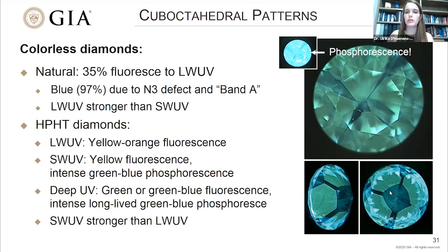Again, these stones are going to have very, very strong, intense, long-lived phosphorescence, which is going to help us flag these stones as potentially synthetic. And by long-lived, I mean very long-lived. Some of them can phosphoresce for several minutes, whereas natural diamonds are going to fluoresce for a matter of seconds. So this is a very, very rare and very neat phenomenon.